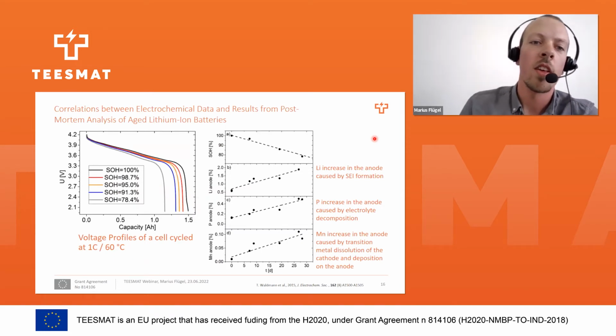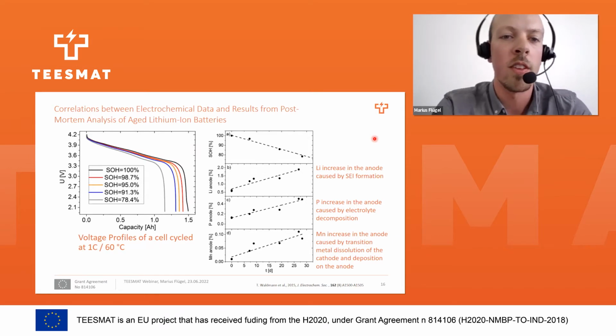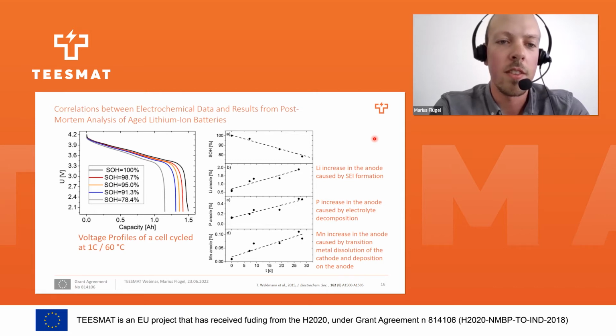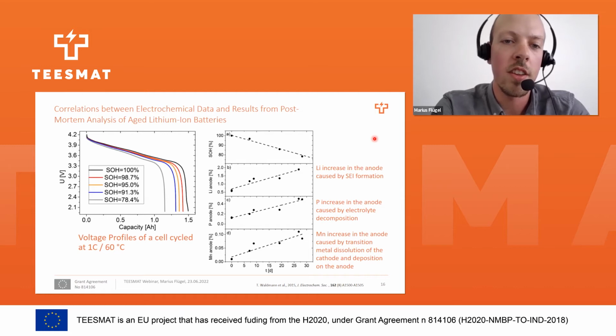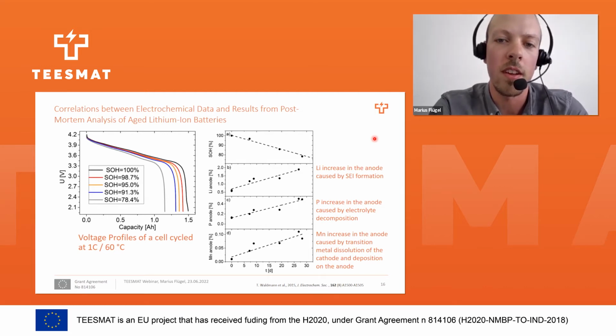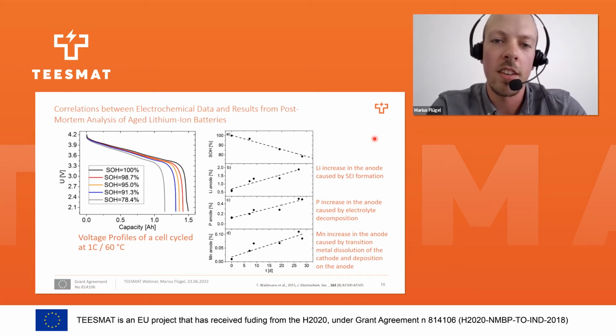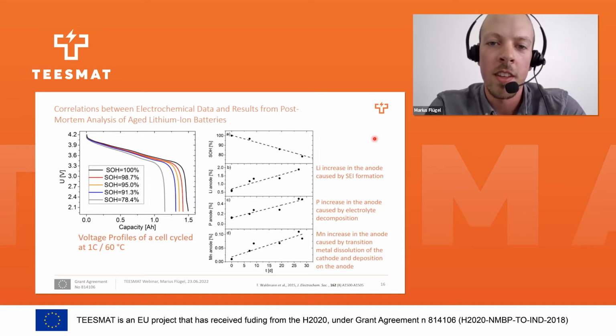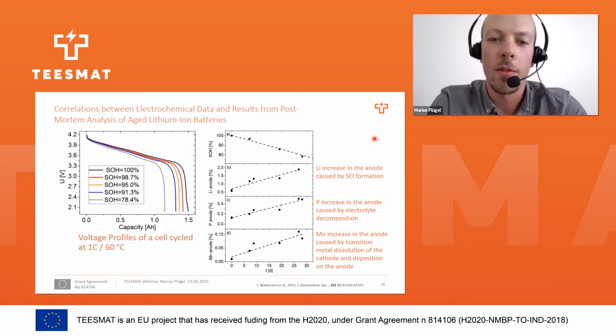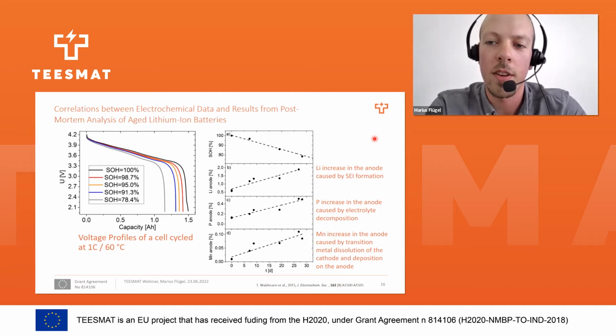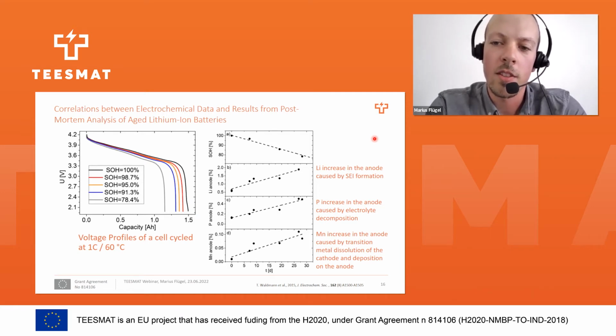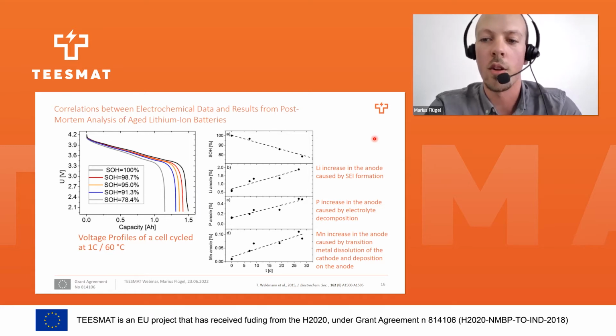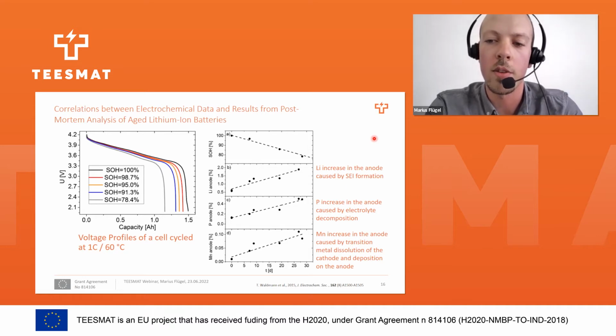To show you the aging effect, we aged several cells until a different state of health. After the aging was over, the cells were completely discharged and then opened, and the electrodes were given to ICP analysis. We saw a correlation with the aging degree and the amount of lithium, phosphorus, and manganese in the negative electrode, the anode. The lithium increase is due to the trapping of lithium in the SEI during prolonged aging. The phosphorus originates from the conductive salt, the LiPF6, which is decomposed during the cycling, and manganese dissolved from the cathode surface and migrated to the anode.